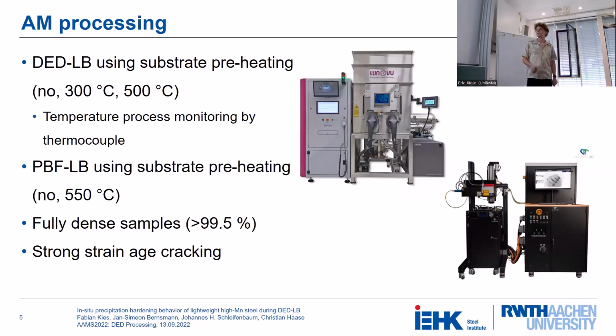Okay, so what types of methods are we using? We are using a DED process with different preheating temperatures. Again, if you're more interested in the processing side of things, maybe ask Jan, or maybe you already know that if you attended this talk yesterday. And we monitored the temperature by a thermocouple. We also applied this material to PBF with no and 550 degrees C preheating. We were able to manufacture fully dense samples, about 99.5% was pretty easily reached.